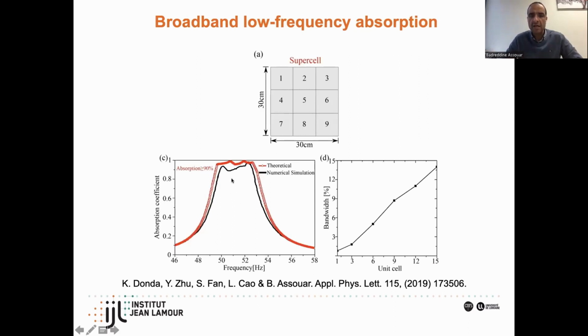This is one of the very easy approaches to enlarge the bandwidth, which means just by overlapping effects. Since we are in the extreme subwavelength range, we can make a supercell, which is multiple unit cells, multiple absorbers operating at close frequencies, which means one operating at 50, the other at 52, 54, and so on. By overlapping effect, we can do that. This is one of the simple strategies, and we still will be in the subwavelength regime. We still can make a huge panel to put in a wall, and it can work in a decent way. But still, it's a kind of local coupling between neighbor unit cells, and by overlapping effect, everyone can do that. But I will come back to this problem about the bandwidth and how we can enlarge the bandwidth, at least in terms of principle.